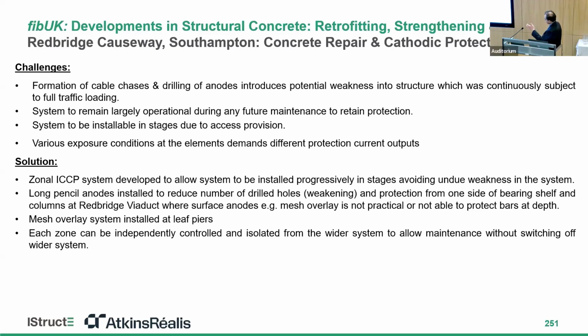So as part of the solutions for the Redbridge Viaduct, we divided the CP system into 40 zones across the elements. In terms of installation of the anodes, in the case of the discrete anodes, we try to drill the anode from one face of the column or bearing shelf or crossheads to avoid redundant, multiple holes and damage to the structure. And for the large elements like a leaf pier, we use the mesh and overlay system to avoid the hand-arm vibration risk, since you may need hundreds of holes and drilling to be done. And then, as I said, each zone can be independently controlled and switched off as and when needed.